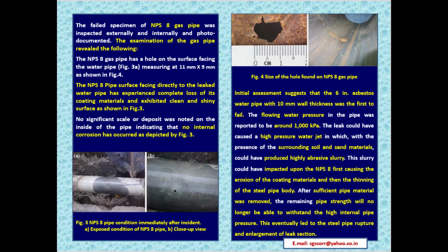You can see figure 3A given at the bottom side. 3A explains the NPS 8 pipe condition immediately after the incident, that is, the exposed condition of the NPS 8 pipe. The NPS 8 gas pipeline has a hole on the surface facing the water pipe measuring 11 mm by 9 mm, as shown in figure 4. You can see the gravity of the erosion pit caused by this water, soil, sand slurry, as shown in figure 4.